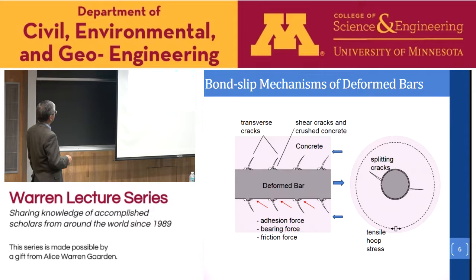And sometimes also introduce some transverse cracks like this. And of course, due to the wedging action of the bar ribs, it could cause tensile splitting cracks like this radiating from the bar, and these are normally suppressed by putting confinement in the column. So we have the tensile hoops here to exert the confining stress to prevent splitting. Otherwise, the bar will get pulled out with tensile splitting failure. So that is not really desirable.